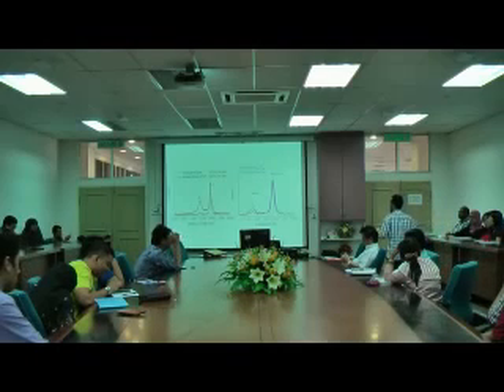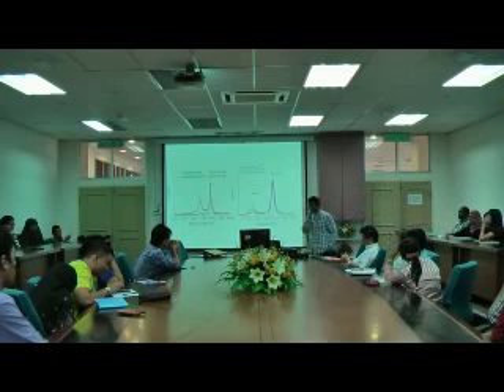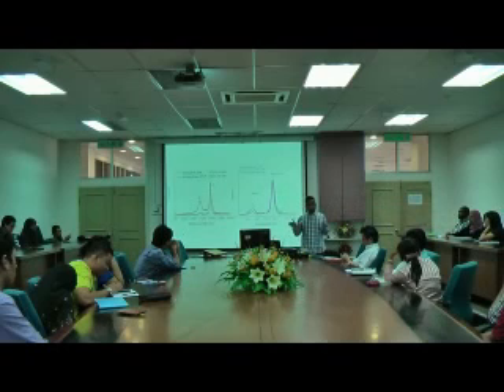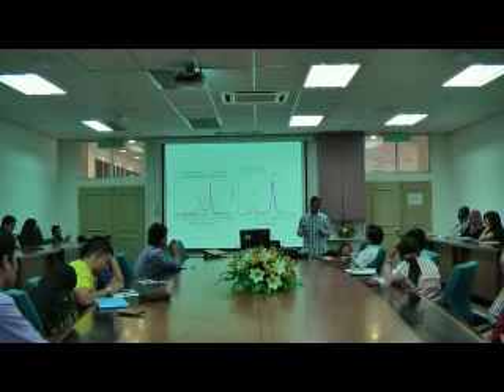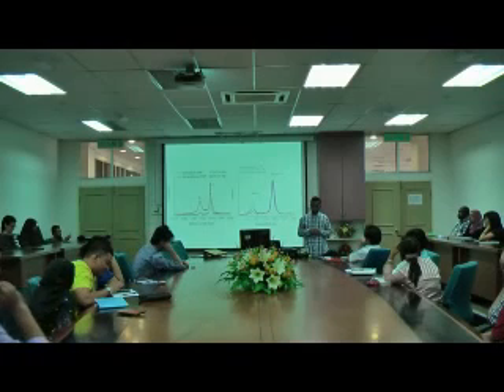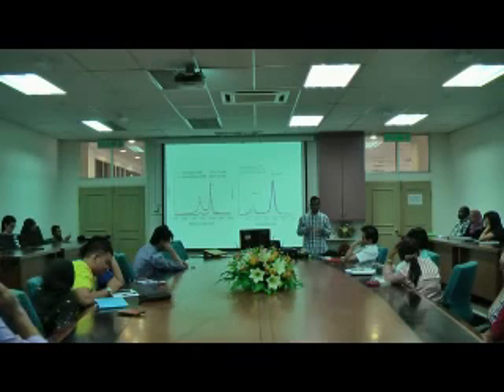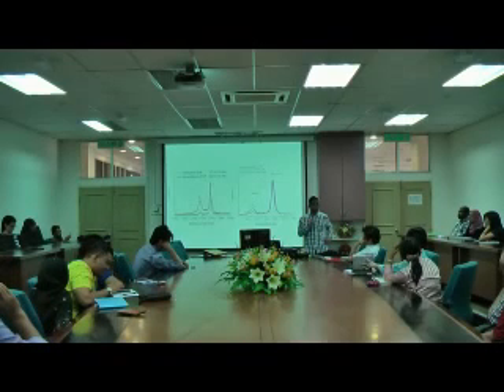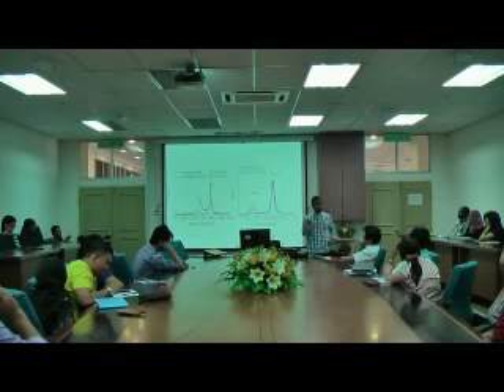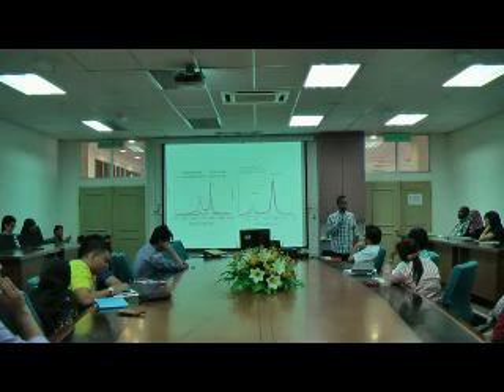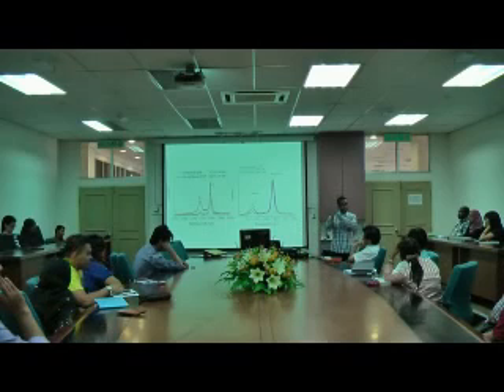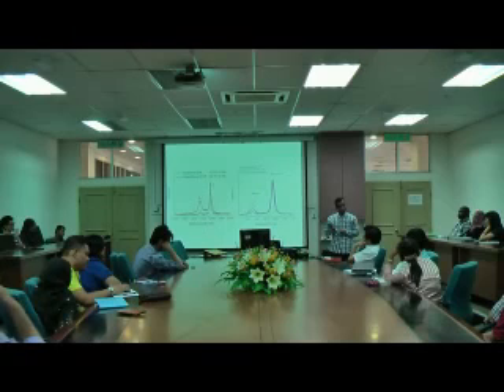That's a good point. No, it's not homogeneous. So there is a variation of the length. It could be due to different reasons. One of them being that the material has a distribution of particle size. If it is something on a support, you will have a distribution. You will not have one particle size. You will have a distribution from 5 to 15 to 20.